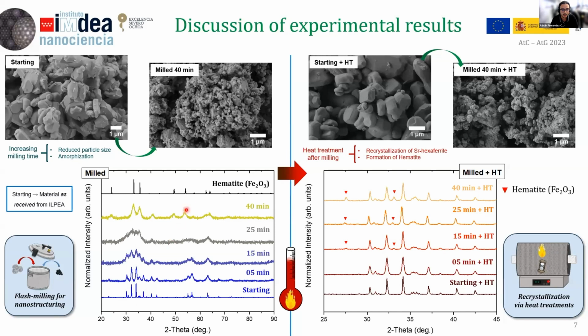As you can see here in the XRD pattern, we start with a clear strontium ferrite structure, and as we increase the milling time, we amorphize the particle surface, and we even managed to transform the initial strontium ferrite phase into hematite phase, a more stable iron oxide phase.